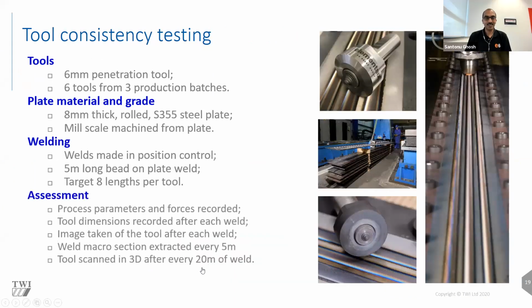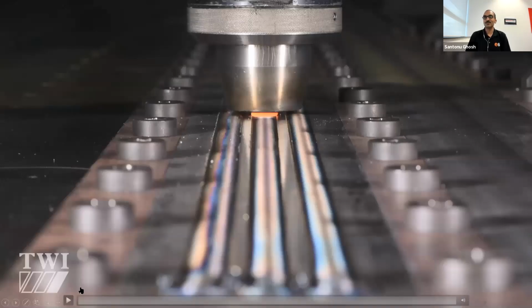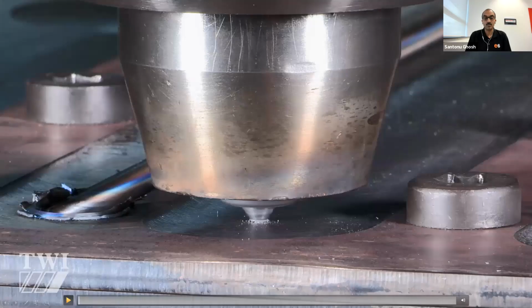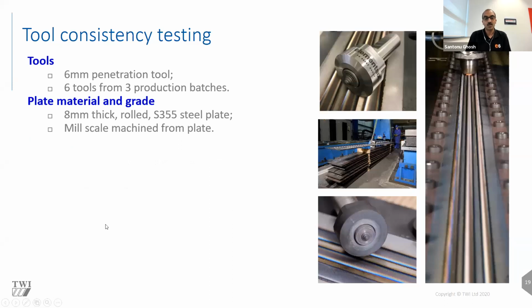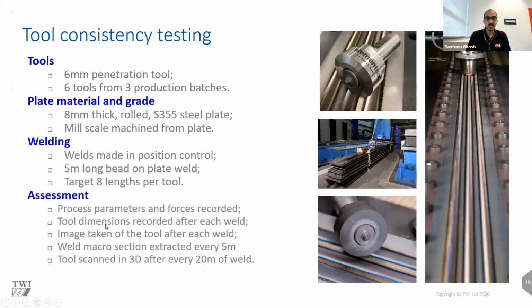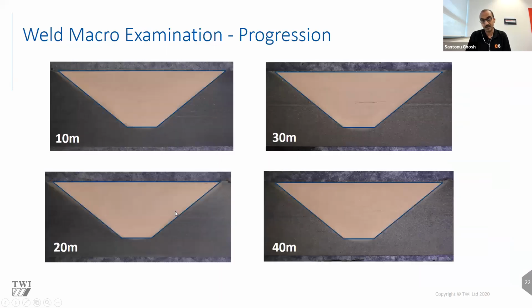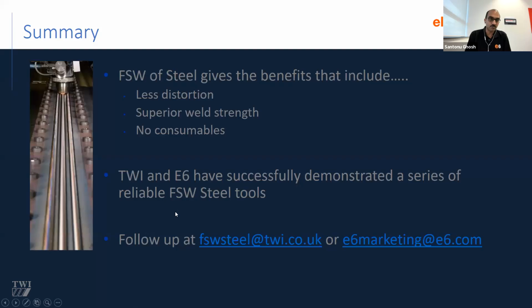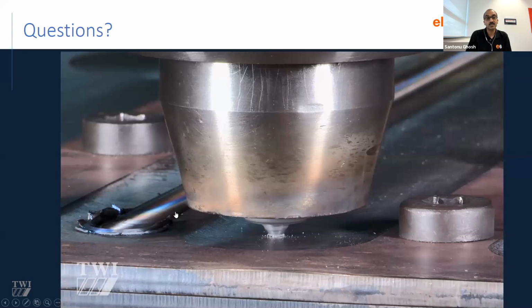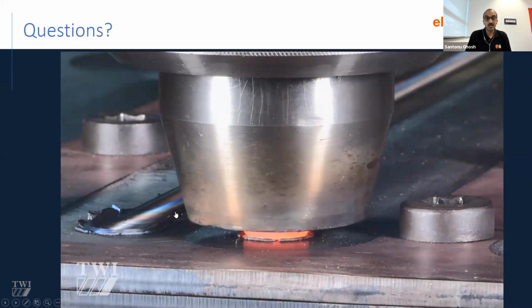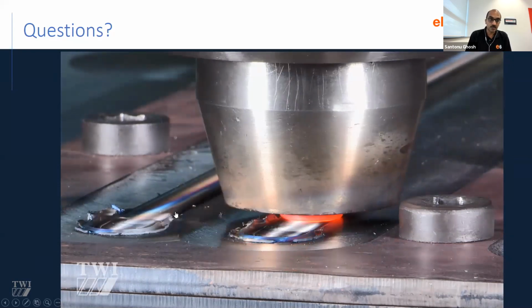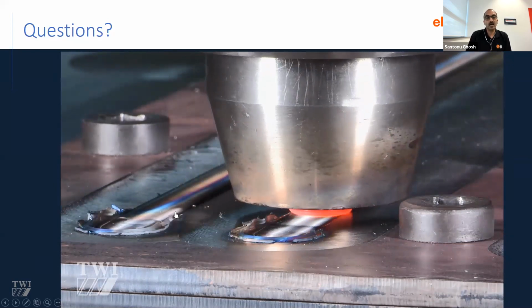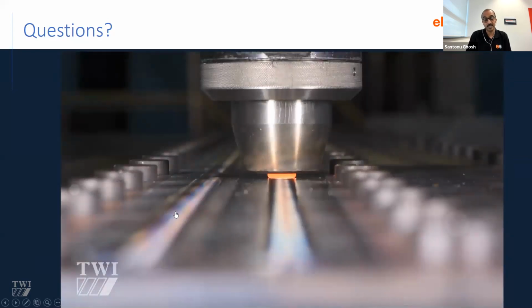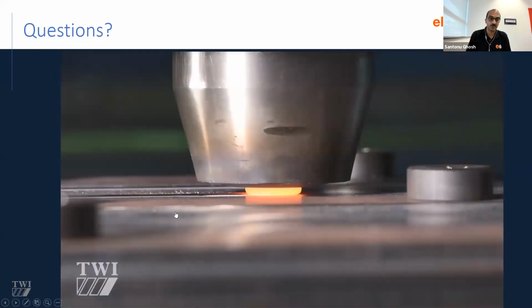So PCBN, I don't know the background, but I'll just tell you, the polycrystalline cubic boron nitride is a composite ceramic. So you have CBN, and then you have the binder phase, we call it. And there are two different broad categories of PCBN. One is low content PCBN, where the CBN content is around 40 to 70%, and then there is high content CBN, where the CBN content increases from 70 to 90%.